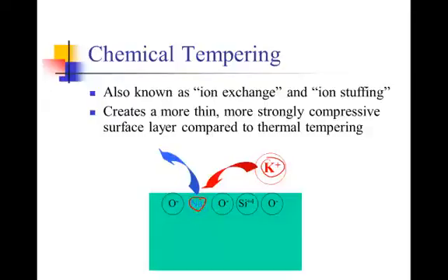But if you introduce any type of crack into the object at all, it will penetrate that compressive surface layer and get into the tensile stress in the interior and cause rapid propagation of that crack through the material, breaking the structure.